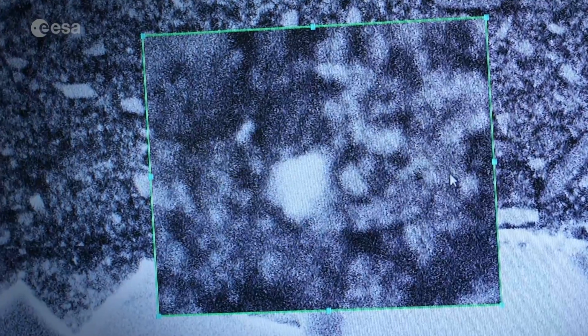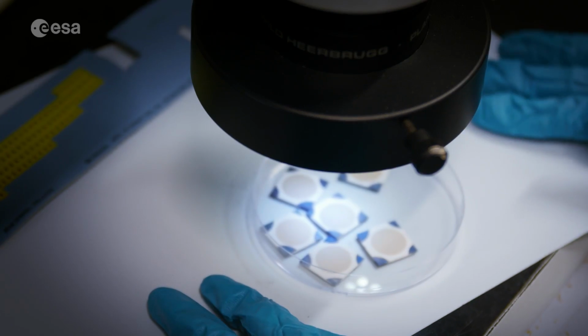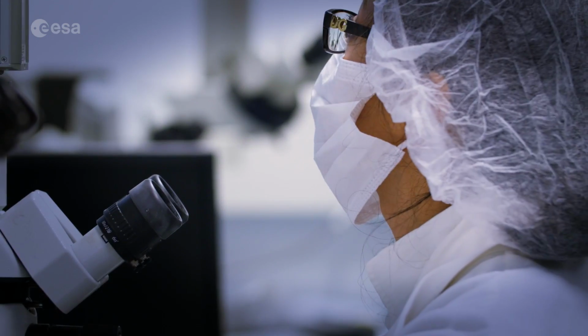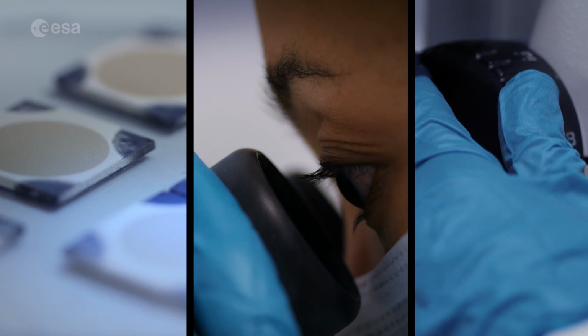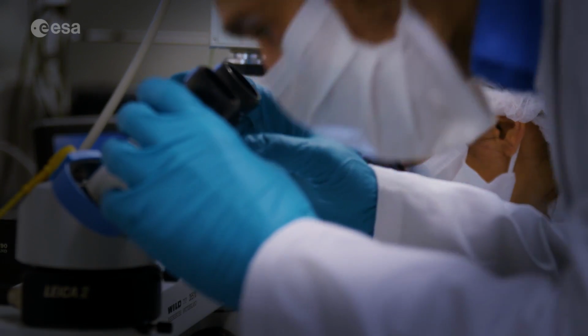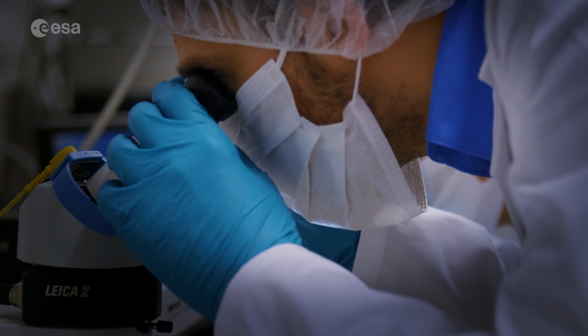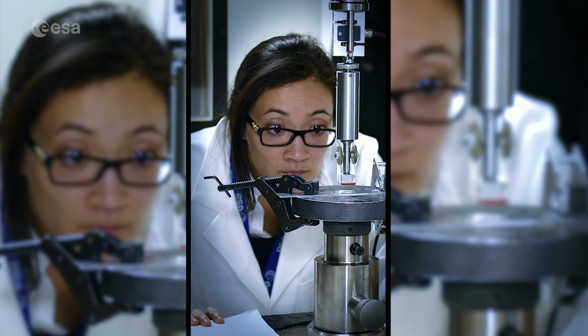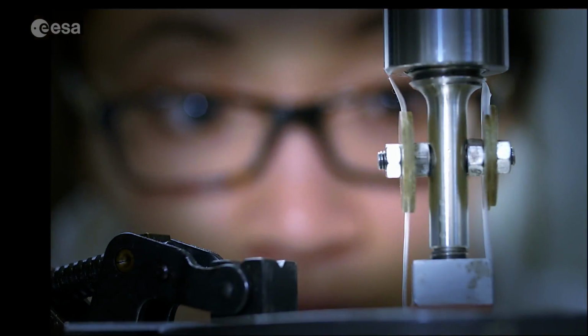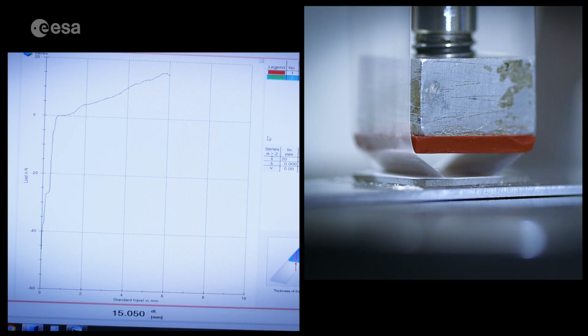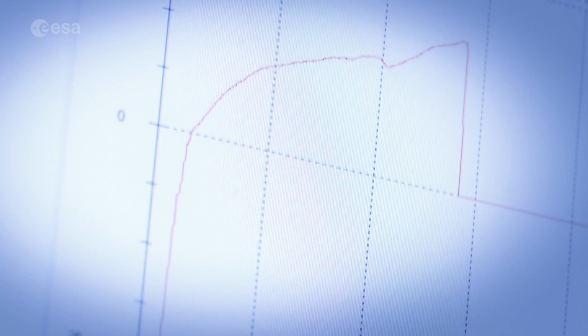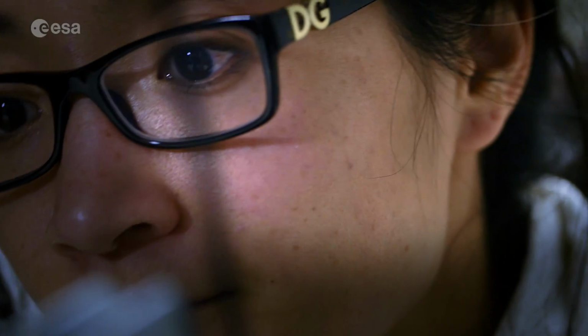Then the samples were mounted on a sample plate and exposed to UV radiation. Visual inspection after UV radiation exposure showed we faced a major challenge. We noted very strong discoloration effects on the first set of exposed samples. We had to carefully analyze these samples to understand the root cause of the darkening. We also checked the adhesion of the coating, applying a tape test to assess whether the surface layer would peel away after high-intensity UV exposure. After improvement, our final coating shows sufficient adhesion strength.